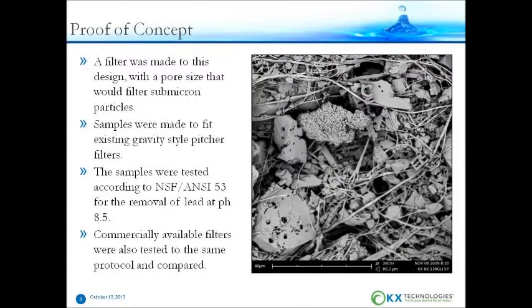To prove out this concept, we made a filter to this design. It consisted of a two-layer media with soluble lead adsorbents and a pore size small enough to remove colloidal particulates on the second layer. The filter was made to fit existing gravity pitcher filters on the market, and then tested to the NSF ANSI 53 standard for lead removal at pH 8.5, along with standard filter cartridges not optimized to remove these complex solutions. This is an SEM image of the first layer of the filter.